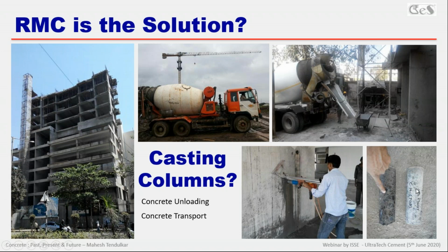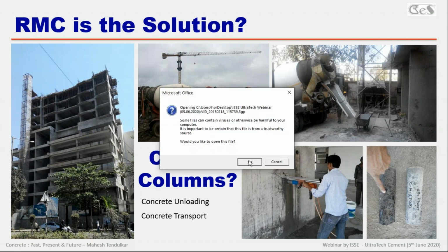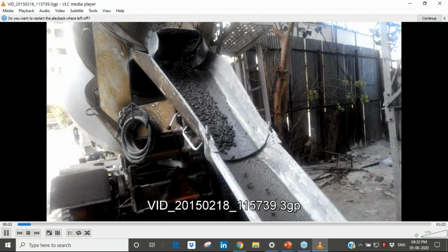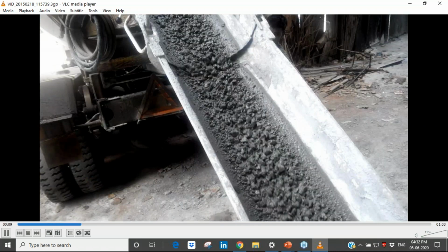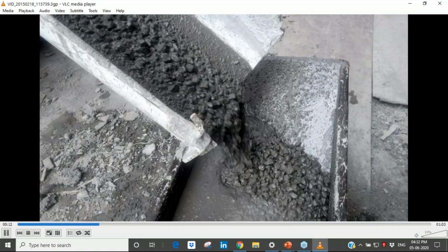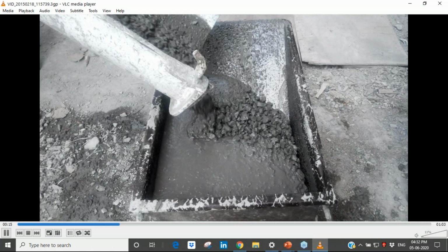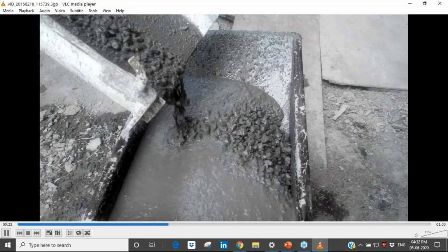Even when we cut this cover zone and tested the core, we found it was not even matching 90% of the required strength. And you can see some clips. I hope you are viewing this clip. This is typical when we go for high-grade concrete: a lot of precaution is needed for the admixture and crushed sand. You can see the concrete itself is segregating even while unloading from the transit mixer. And then this concrete will be taken to the higher level by this winch.